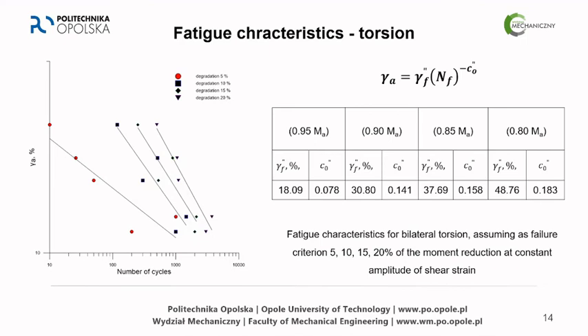And a similar analysis has been prepared for the torsion. And here, however, you can see that for degradation 5% there is one shape of this curve, and for 10, 15 and 20 they are parallel to each other.